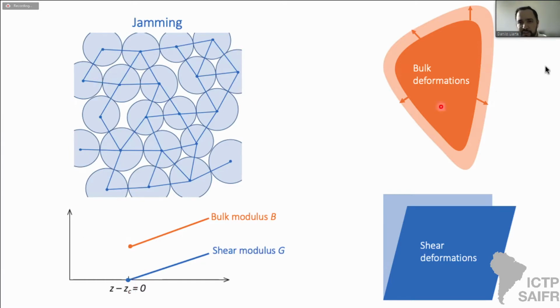And just as a quick reminder, it's traditional to decompose general deformations of an isotropic body into bulk deformations in which there is a change in the volume, and shear deformations which do not involve changes in the volume. At Z equals ZC, the bulk modulus jumps to a finite value, whereas the shear modulus grows continuously from 0. Using jargon from statistical mechanics, jamming seems to have this peculiar mixing of first and second order phase transitions.